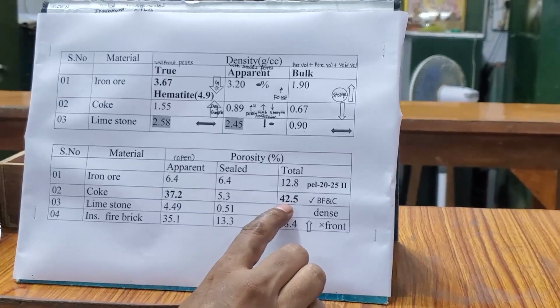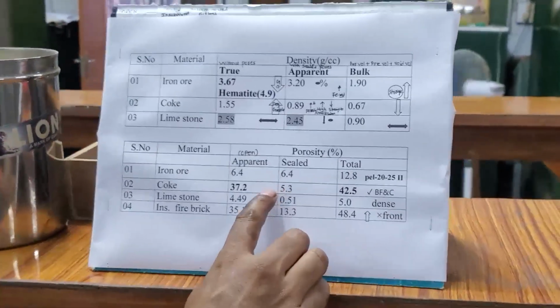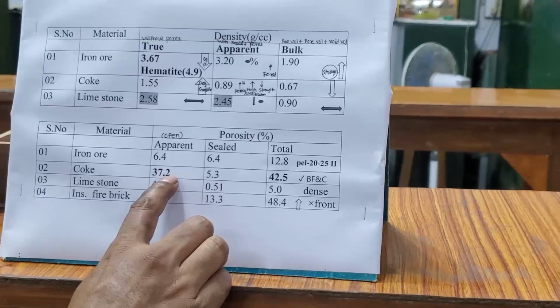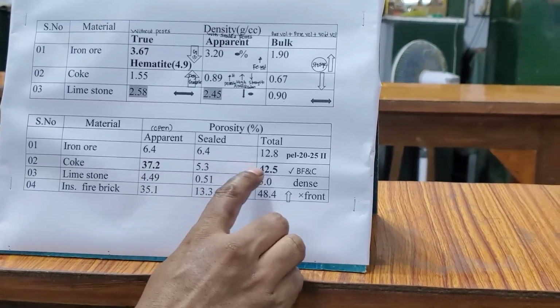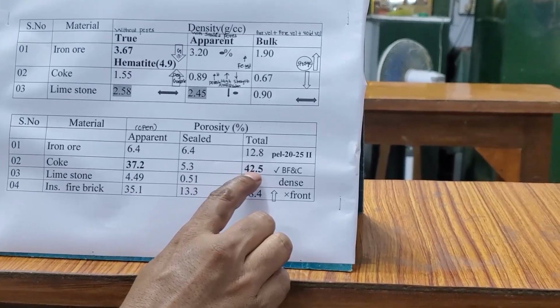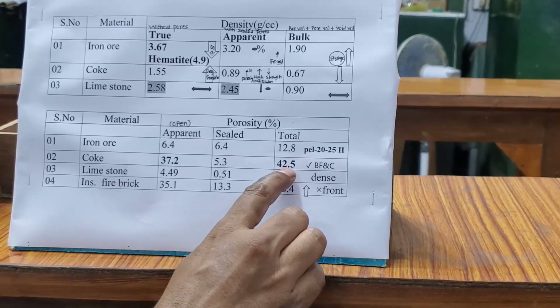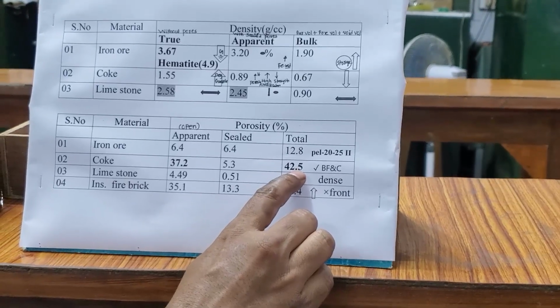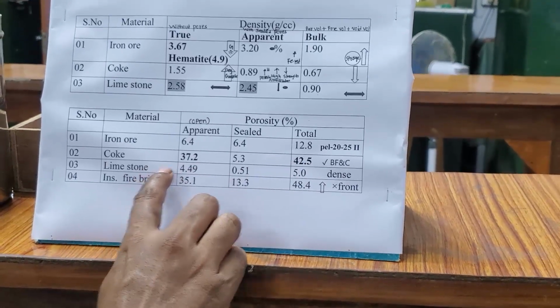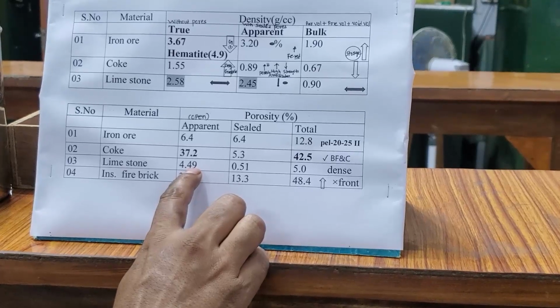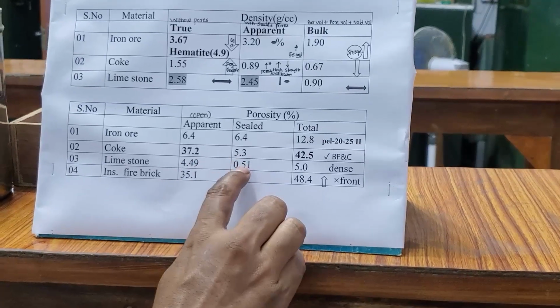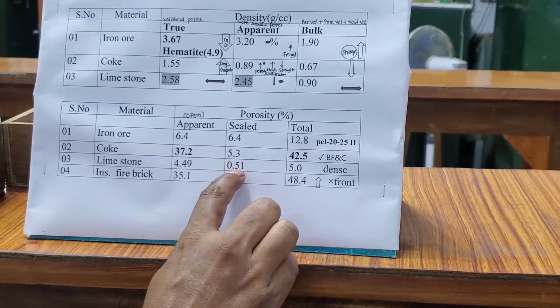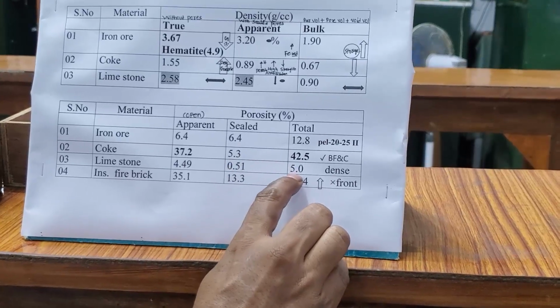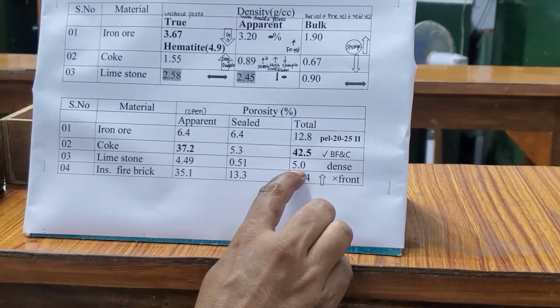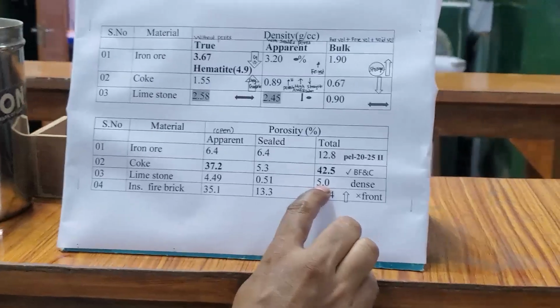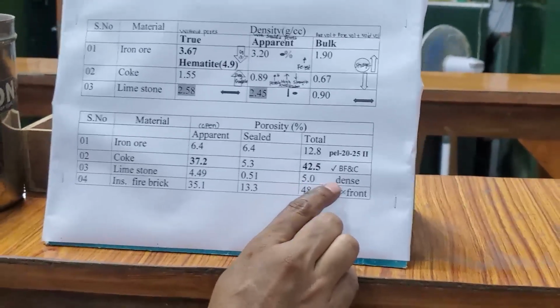Coke, if you are seeing the apparent porosity, the open porosity is 37.2, which is very high, it's very good. That's why the total porosity we are getting is 42.5 for coke, meaning it is good for blast furnace and cupola. Limestone, apparent porosity is 4.49 and sealed porosity is 0.51. It is totally 5. It means the porosity is very low, so limestone is a dense material.